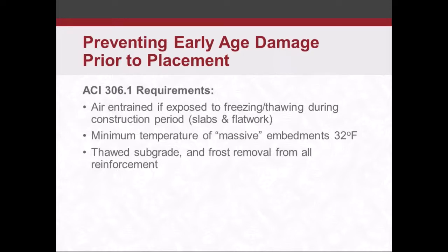Minimum temperature of massive embedments: we want to make sure that it's not below 32 degrees. Concrete's not going to bond well to frozen rebar. We want to make sure that it's bonding well to the reinforcement, and we want to make sure that the subgrade is thawed, with any kind of frost removed from all the reinforcement. Thawed subgrade: you cannot place concrete on frozen subgrade, as ACI 306.1 states. So the subgrade should be thawed prior to concrete placement, and that can be done a number of different ways.